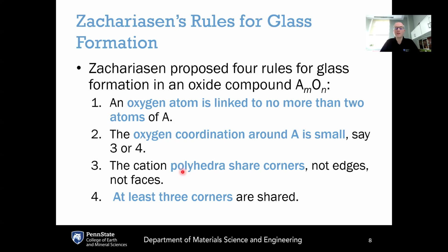If they were to share edges or faces, this would lead to a greater propensity for crystallization because it leads to a more closely packed network. Zachariasen deduced that a glass network, because of its disorder and because of its somewhat higher internal energy, needs to have a somewhat more open structure compared to the crystal. And we can get that open structure if the polyhedra are sharing corners rather than sharing edges or faces.